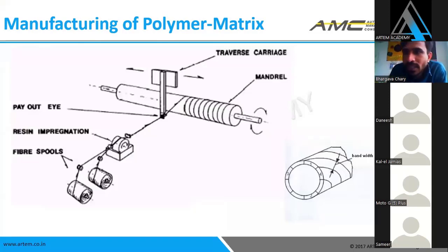So this is filament winding, as I've told you a lot regarding the hydrogen tanks. These hydrogen tanks, in general, like the LPG cylinders we have at home, have an internal core, and then there will be winding. To give you the process, these fiber spools, similar to pultrusion, will be mixed into the resin and then come out. The mandrel goes in the transverse direction and also in the rotational direction. With the help of tension, the fiber can spread in all directions.